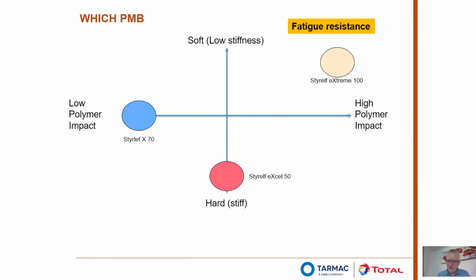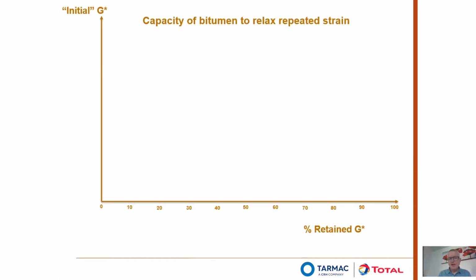If we now start thinking about fatigue resistance, we see a very different picture, because we see the fatigue resistance improving as we go softer in the bitumen, and again improving as we go up the polymer impact scale. So when you're thinking about fatigue resistance, you wouldn't necessarily choose an X70 bitumen. You might consider your Styrelf eXcel 50 because you've got that polymeric impact coming into play. But you'd certainly consider the Styrelf Extreme 100 because it's not only low stiffness, but it has a huge amount of elastic recovery.